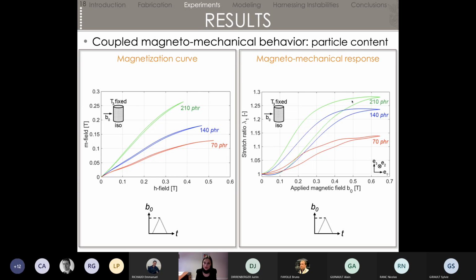And another point with those materials: the more particles you put, the more magnetostriction you get, so the more strain induced by a magnetic field. However, as you keep increasing the amount of particles, you do not get a linear effect. So if I keep putting particles, I'm not going to get larger and larger magnetostriction.